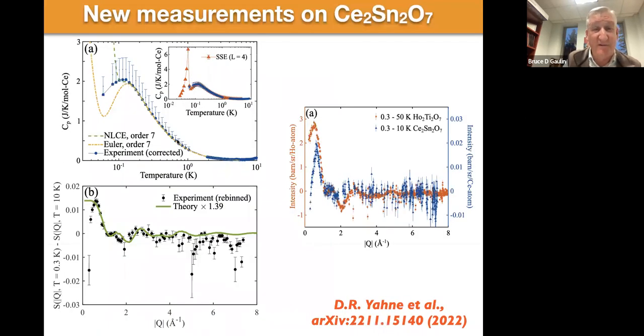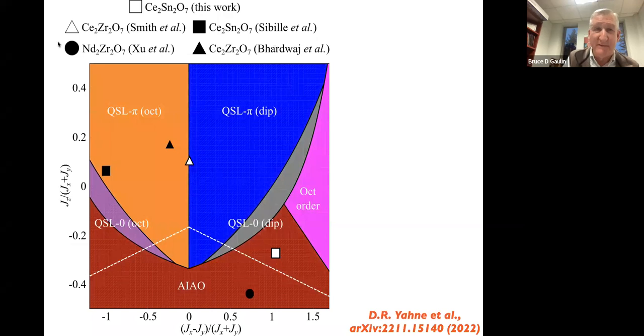We've gone through this exercise of estimating the microscopic spin Hamiltonian, mostly from the heat capacity, but also using susceptibility data and this diffuse scattering for consistency. And then we can put cerium stannate on this same plot. It comes out down here where this open square is. In this region of the phase diagram, if you go to low enough temperatures, you should get a conventional Néel state. It's not a quantum disordered state.